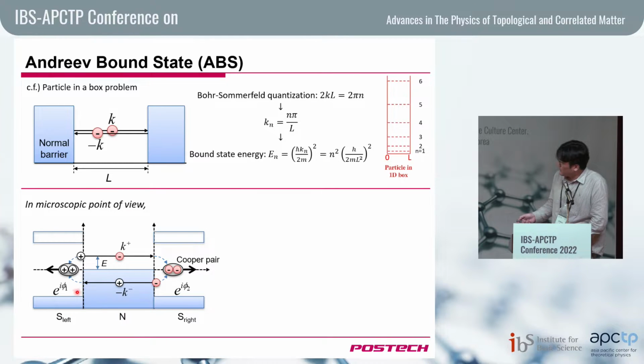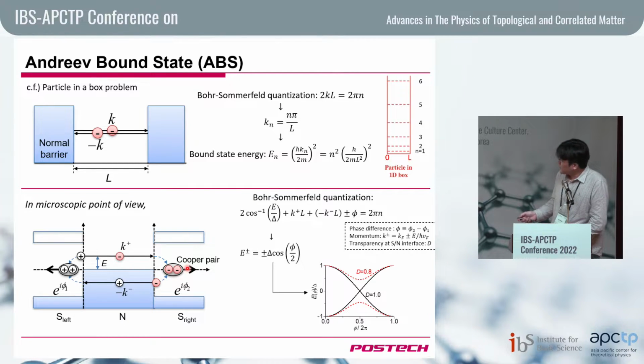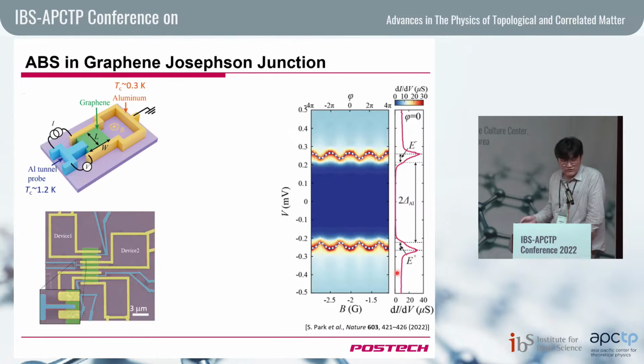And the hole can also undergo another Andreev reflection, getting back as an electron into the original state. When that happens, one round will transfer one Cooper pair from the left to the right superconductor. This is how Josephson current can flow. And the phase accumulation for this electron can be written in that way. On top of this dynamic phase, you will also have the superconducting phase. This phi is the phase difference between these two superconducting electrodes, okay? Which we can control. And that will give us this interesting shape of the Andreev bound state spectrum, which can be tuned by the phase difference phi between these two superconductors. So that's our bound state we want to look at.